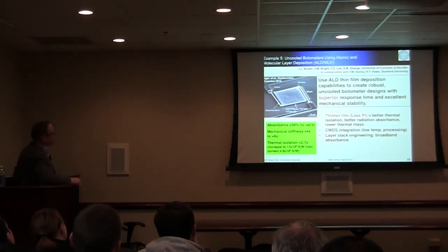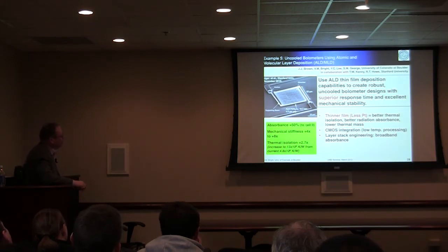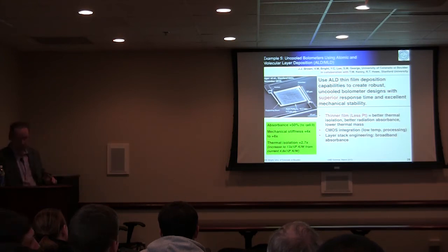So the bolometer work, this is something we're collaborating on with a Stanford group. This is an ALD platinum device, just made out of platinum. The idea with this bolometer is that one has to get the thermal time constant down. So the smaller the mass, the smaller the time constant, the better the overall figure of merit. And so here the platinum is used both as a detector, as the membrane, as well as a piezoresistor. Those are 2 tethers right there.